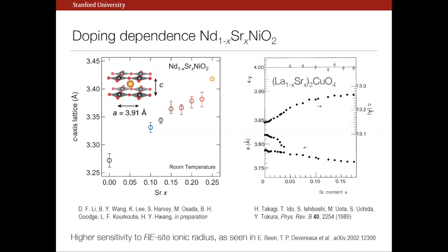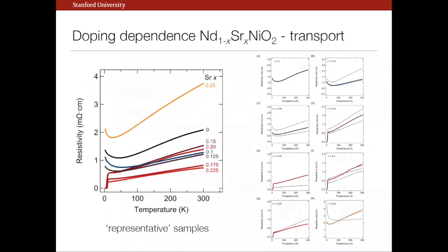In any case, here's a first statement I think we can make now about the doping dependence of the system. So if we look at the c-axis lattice parameter, these aren't error bars, but this is like 3 to 5 samples, and these are the extremal values for a given one with respect to the average. So with this kind of a spread, it's pretty well reproducible, monotonically varying, qualitatively similar to the cuprates, with the caveat that it's about 3 to 5 times larger. And this notion that there's a higher sensitivity to rare earth radius has been seen in work of Tom's student, which you can find as well. Okay.